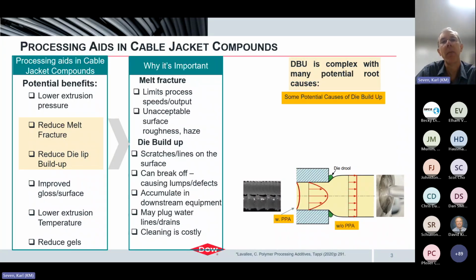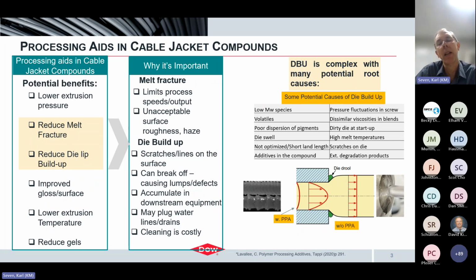much reduced by the use of certain processing aids. Now, unfortunately, die lip buildup is a very complex problem that has many root causes. I won't get into all of the potential root causes, but typically they're broken down into three main areas. One is machine related, which focuses on the die, the design of the die, both internal and external. It can be processing related, in terms of temperature profile, how the compound is extruded. But it can be material related. So in other words, the components used in the jacketing compound, or the resin in the jacketing compound, or both of which. Now, in this presentation, I will focus pretty much exclusively on the material related or the compound related problems that can relate to die lip buildup.